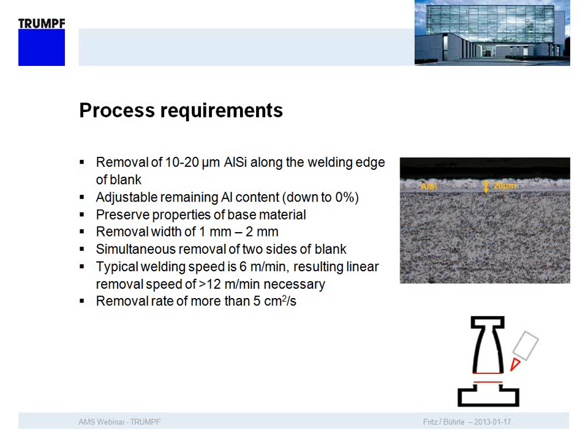Also a requirement could be the simultaneous removal on two sides of the blank. That means you have to take off the layer on the upper side and the bottom side, just to make sure that no aluminum is going into the welding seam. A typical welding speed in the tailor welded blank machines is around 6 to 8 meters per minute, so the resulting linear removal speed should be around 12 meters per minute, counting the upper and the bottom side, so as not to create a bottleneck in the process.